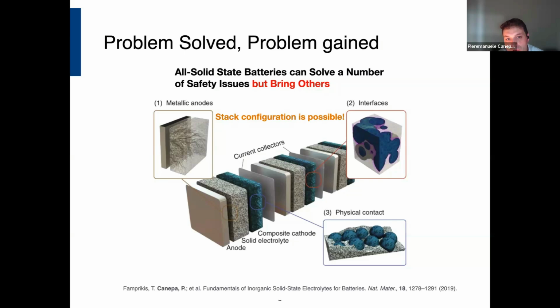And here I just wanted to show you, for example, the interfaces, or stabilizing heterogeneous solid-solid interfaces, where solid could be the solid electrolyte displayed here as a marble type of texture, and lithium metal anode or sodium metal anode, effectively. Of course, there are also some design advantages which one can tap on when using a potentially working all solid state battery, is that you can utilize current collector, but this current collector, if appropriately designed, can accommodate stack configuration in this sodium all solid state battery.